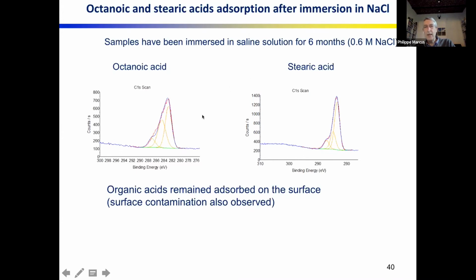Now we look here at the surface after immersion in sodium chloride for 6 months. And you can see that for both octanoic and stearic acid, there is still a signal associated with the organic acid, which can be observed by looking at the high binding energy where we observe the carboxylate group. So in both cases, the molecules are still there. However, there is also some surface contamination in addition to the presence of the organic acids.